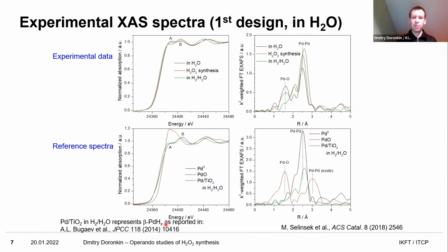So there are two kinds of hydrides. If we are talking about palladium alpha hydride and beta hydride, the difference is that in the alpha hydride, we do not have the lattice expansion of palladium. So X is within or below 0.3, and above 0.3, we have a bulk hydride formation with lattice expansion.